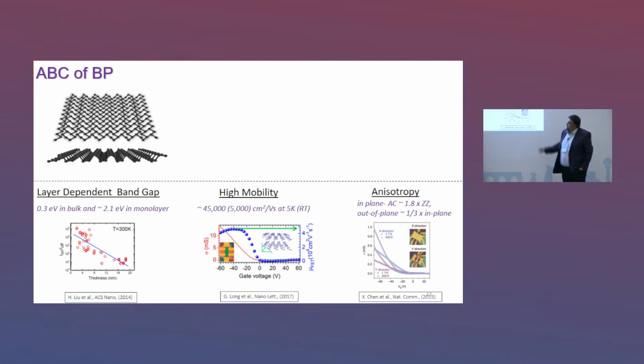And there have been some studies showing that if you send the charge current from here to here, versus here to the other edge, the mobility of the devices changes. Because it's a highly anisotropic material, the charge transport, and later on it was shown that optical properties, everything depends on the crystal direction.